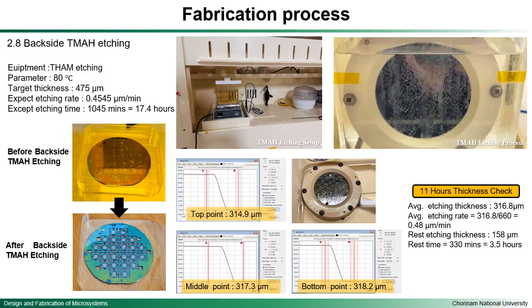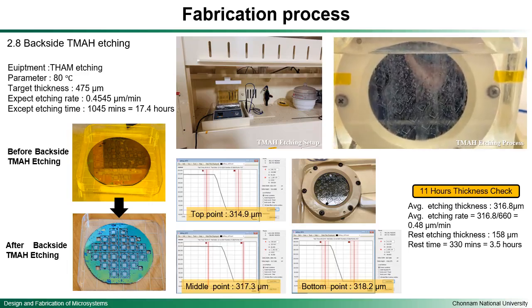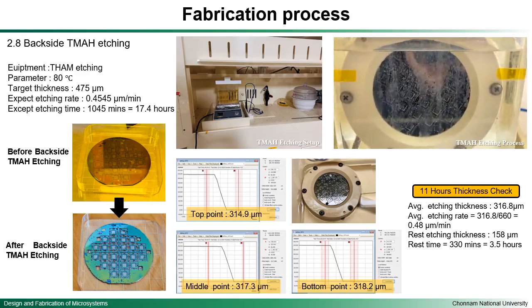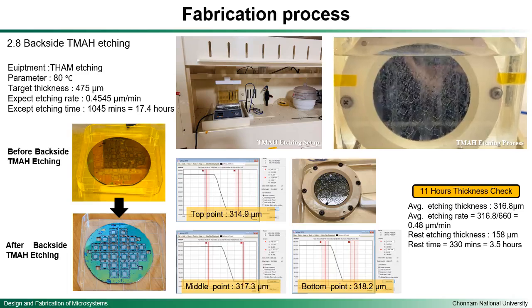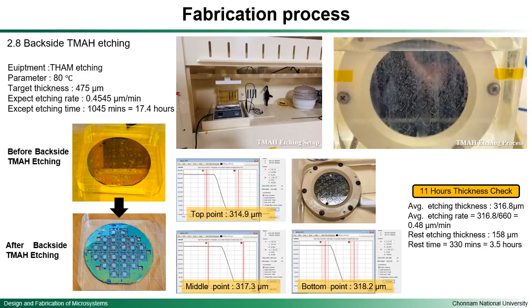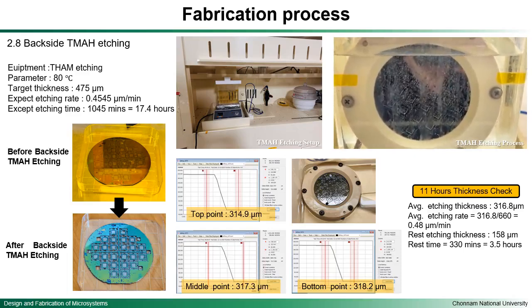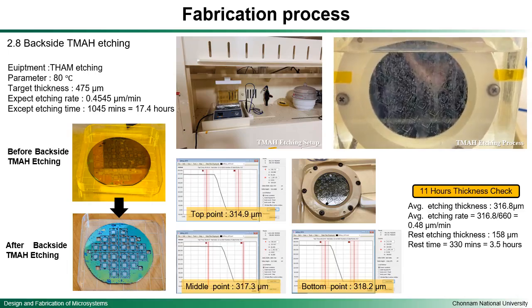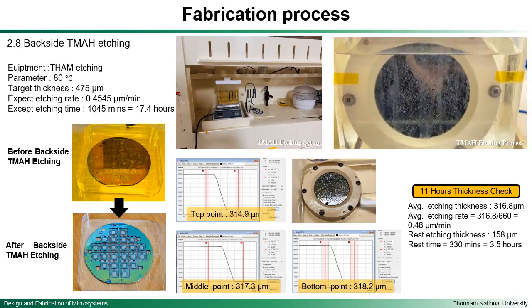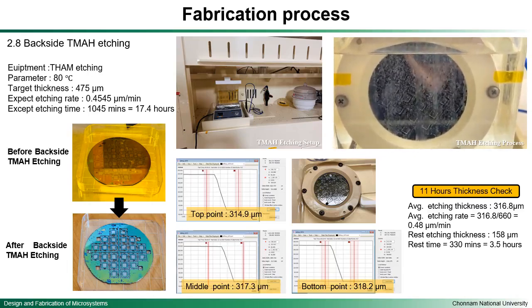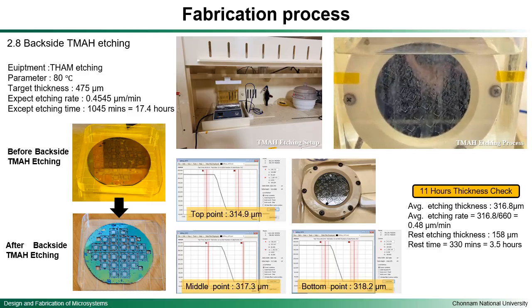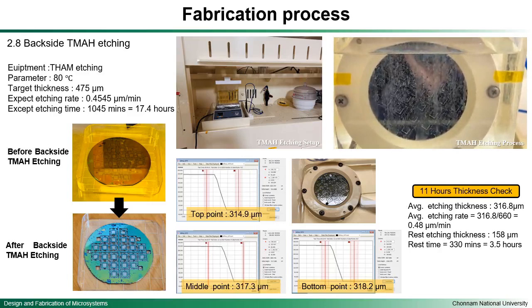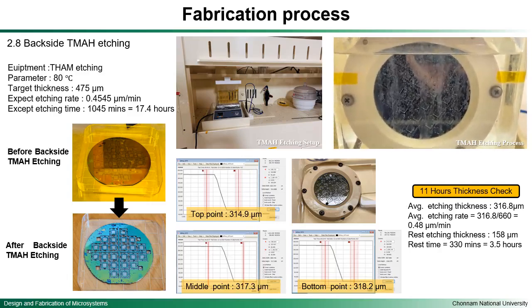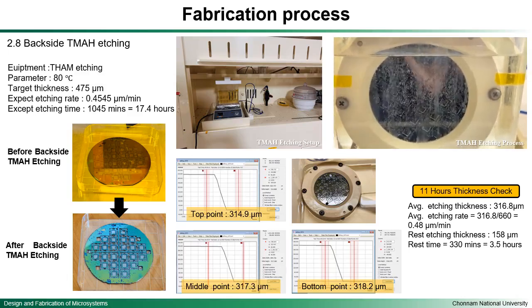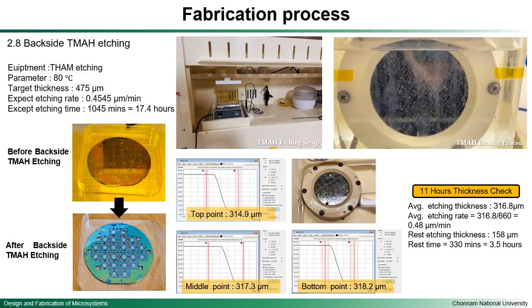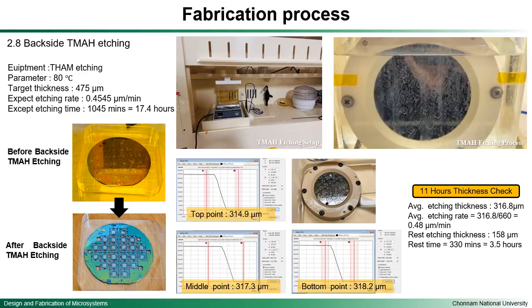Based on the previous expected etching rate, we calculate the expected etching time, which is around 17.4 hours. But because the time is too long, and even a small error in the etching rate can maybe cause the diaphragm to break, when the TMAH etching had gone on for about 11 hours, we tested the thickness first to make sure the etching rate is desirable. Here I tested 3 different points of the wafers.